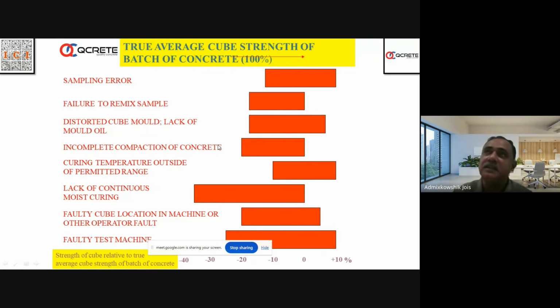As I said, each 1% of unremoved air content will lead to 5% drop in strength. So if somebody has not compacted properly, let us say 5% voids are there, it may lead to 25 to 30% loss of strength, which is apparent loss of strength. And this may be the same case on site also. If the compaction is not done on site properly, it may lead to similar issues.